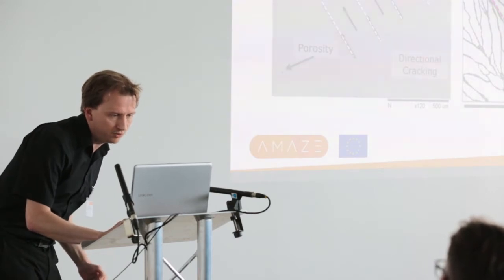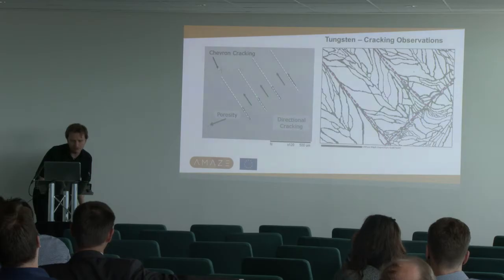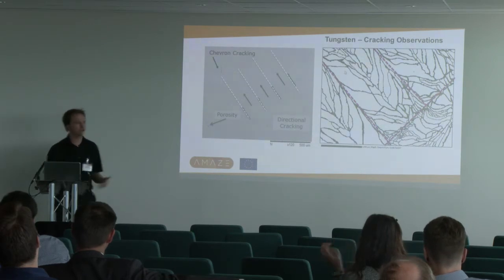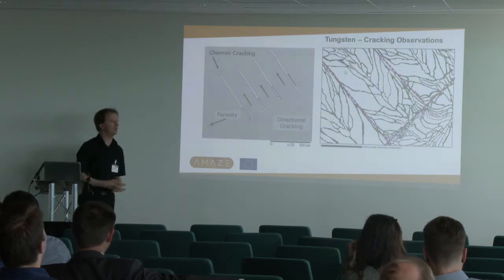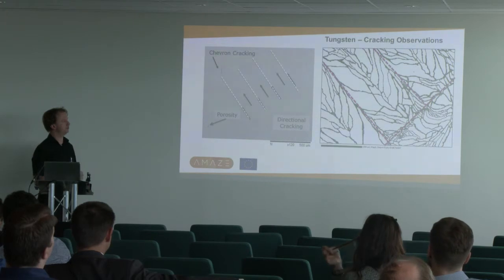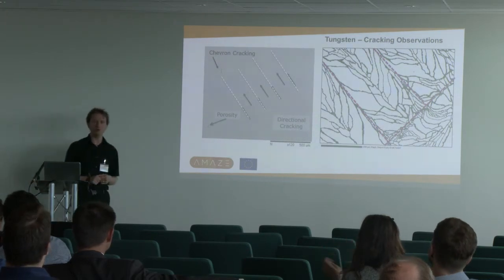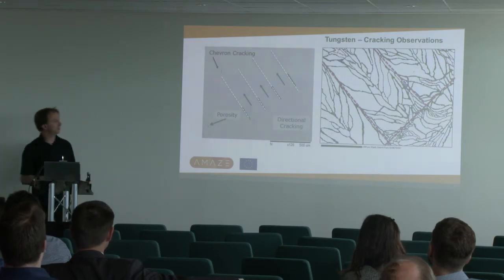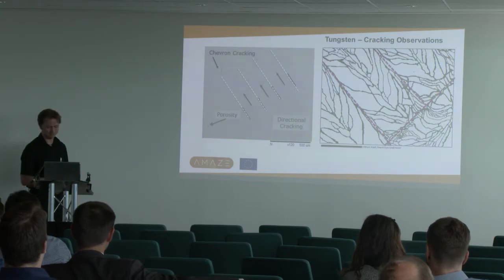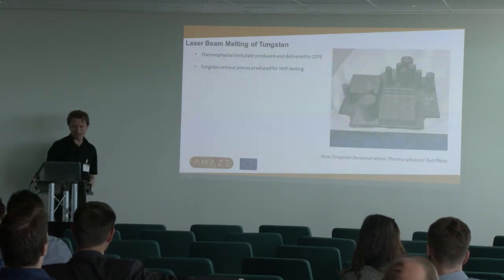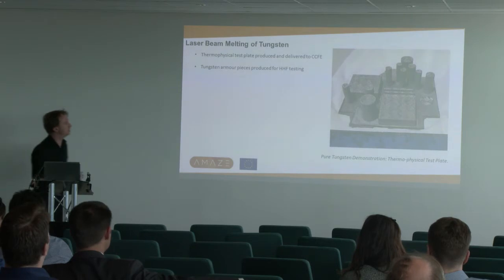You can see we've got some centerline cracking here and this chevron cracking, which corresponds to our grain structure. So it's where we'd expect the cracks to open up. There's talk of doing things like an atom probe to really get to the root cause of what's happening at those grain boundaries, and hopefully propose some ways of getting around it once we understand it better.